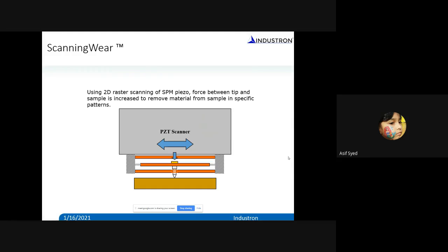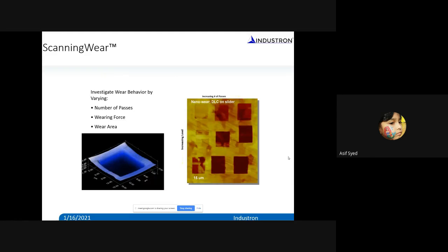And in the next step, if you want to understand the wear properties of this material, while you do the imaging, you can progressively increase the load and wear the material there and then. For example, if you have a multi-phase material and you want to know the wear property of one phase with respect to the other, you can go and wear that particular phase. Because we have the imaging capability, you can calculate the wear volume directly from the image. In that way, you can also extend this to understand the tribological characteristics of the material.